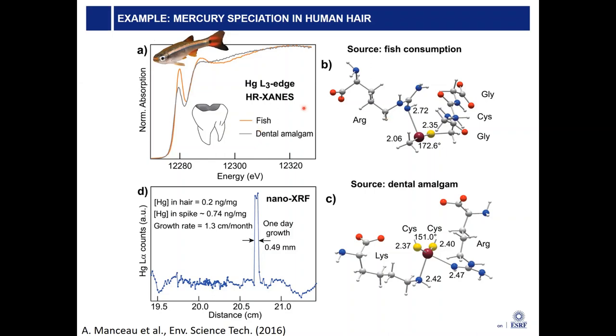And the point here is that the local coordination, so these are proposals how mercury is coordinated, if it ends up in your hair after fish consumption, and if it ends up in your hair after having your dental amalgam removed. And you see that the coordination is different in the two cases. And the assignment between the structure and the spectral shape is in this case done by measuring many, many, many model compounds. And theoretical calculations, so first structure optimizations, and then the structures inserted into a theoretical code, in this case the FDMNES code, and this then leads to this assignment of the spectral features to the two complexes here.